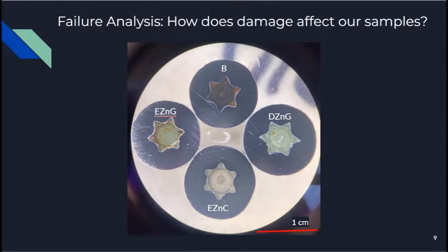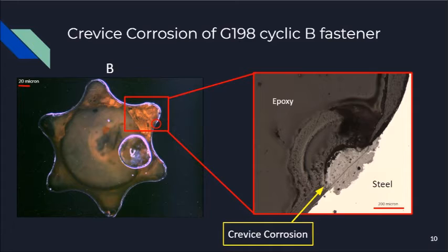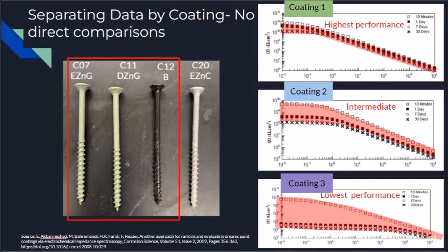and time. And then, transitioning to our failure analysis portion, this is a top-down view of one of our mounts showing the heads of each fastener. These samples were used to analyze how driving into treated lumber affects their performance, as well as to assess the corrosion mechanism. We determined that the corrosion mechanism was crevice corrosion, and this is an example of a fastener that was driven into treated lumber and underwent a long-term corrosion test. The driving created crevices of damage at the midpoints, which are circled on the slide, and they were ideal environments for corrosion.